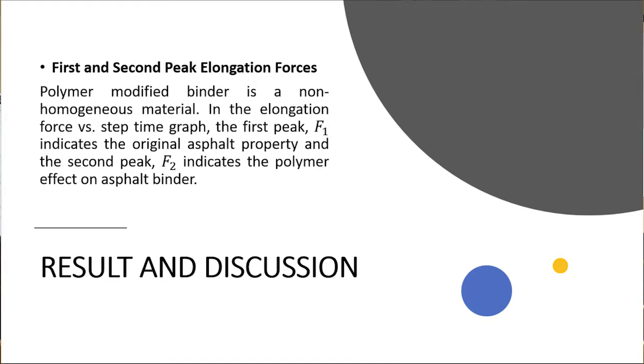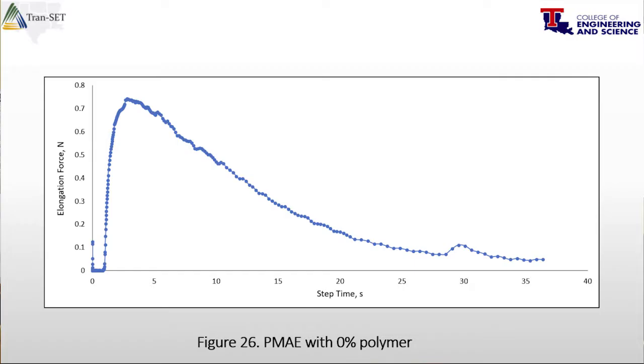Okay, now when it's stretched enough, when you try to tear it apart, the polymer engages at that time. So the second one actually gives you the polymer modulus. The first peak comes from the asphalt modulus. So one is asphalt modulus, one is the polymer modulus. You can calculate polymer modulus from this data also. And then we use F2 by F1. Why second peak over first peak? I will explain it later.